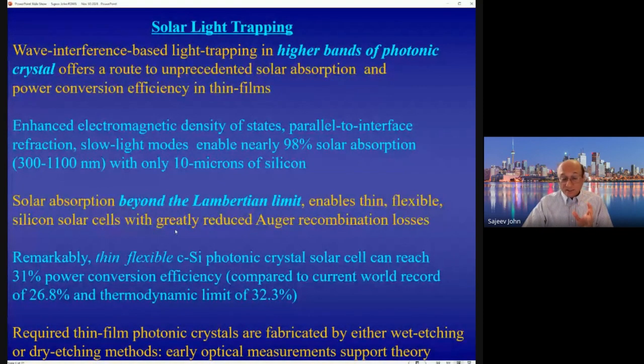And this reduces recombination losses, such as Auger recombination, because it's much thinner. And remarkably, we predict that these thin, flexible silicon solar cells made in photonic crystal architectures could reach, in principle, efficiencies as high as 31%, compared to the current world record of 26.8%, which is based on a cell which is over 100 microns thick, and the thermodynamic limit of 32.3%.